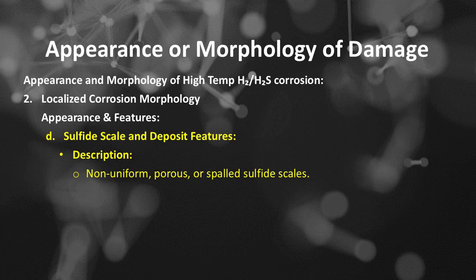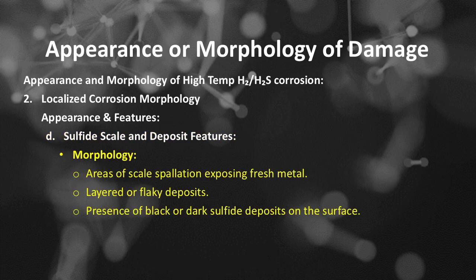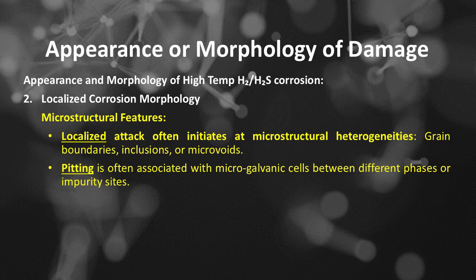The number D of the appearance and features of localized corrosion is sulfide scale and deposit features. Non-uniform, porous, or spalled sulfide scales. The morphology of sulfide scale and deposit features: areas of scale spallation exposing fresh metal, layered or flaky deposits, presence of black or dark sulfide deposits on the surface. The microstructural features of the localized corrosion morphology: localized attack often initiates at microstructural heterogeneities, grain boundaries, inclusions, or microvoids. Pitting is often associated with microgalvanic cells between different phases or impurity sites.